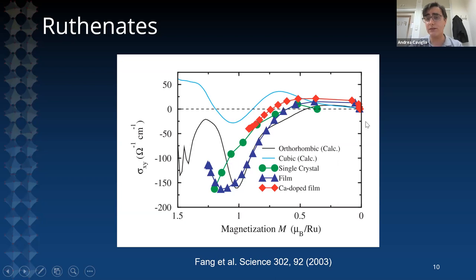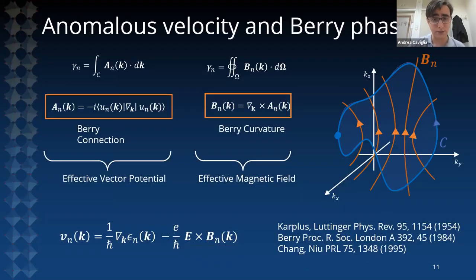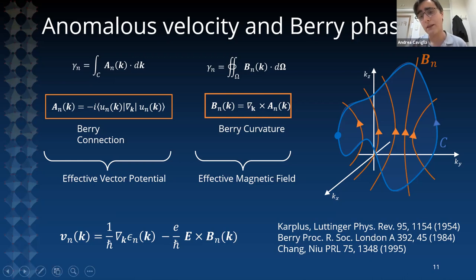It was already in 2003 that an unusual behavior of the anomalous Hall effect was pointed out in this system. As the system magnetizes, the anomalous Hall effect experiences a sign change. At low magnetization and high temperature, you have a positive anomalous Hall response. Then as the system magnetizes or you reduce its temperature, you observe a sign change to a negative anomalous Hall response. This was understood as the anomalous Hall effect being derived from a source of Berry curvature. Such effects are typically observed in systems with either inversion symmetry breaking or time-reversal symmetry breaking.